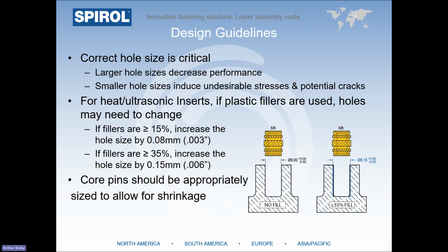In the example shown to the left, no filler is being used and the plastic is polypropylene. Noting the recommended hole size for an M6 heat installed insert is 6 millimeters plus 0 minus 0.08 millimeters. However, if that same component was made of nylon 6/6 with 35% glass fill, we'd recommend adjusting the initial hole size up by 0.15 millimeters.